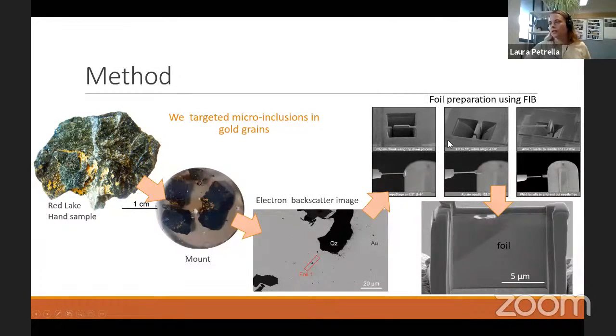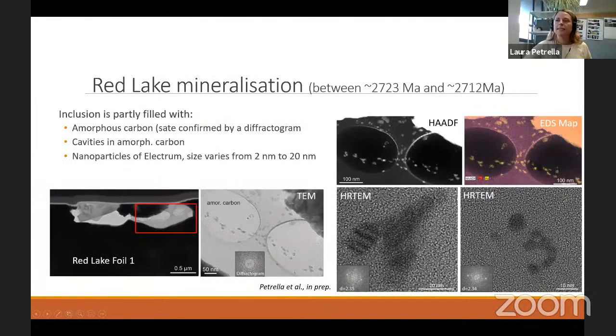This is how we extract this very small sample that we call a foil. You can see that this foil is actually coming from this sample. The bright spot that you see here is the inclusion we targeted, and it is all surrounded by gold. This is a TEM image from the same sample I just showed previously. This is a zoom on the inclusion, and that is the area we are interested in.